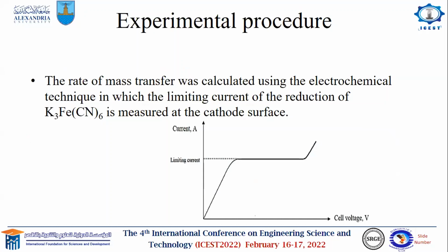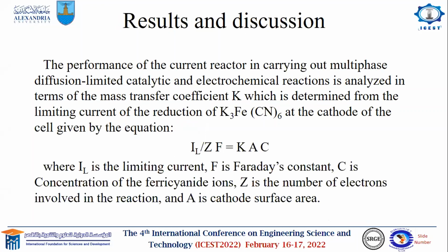The rate of mass transfer was obtained using an electrochemical technique in which the limiting current of the reduction of ferricyanide at the cathode surface was obtained from the polarization curve, constructed by a stepwise increase of the current and measuring the corresponding cell voltage until the plateau of the limiting current is reached. Mass transfer coefficient is calculated from the limiting current equation as follows.